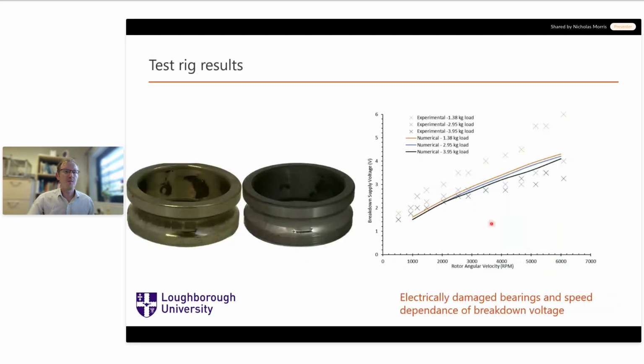So these are some results that we could show just to give an indication of what we can see through the test rig. On the left-hand side of the image here, we have a bearing damaged by applying the electrical voltage across the shaft. And this occurs in less than a day. I think this took 7 hours or something, continuous running at fixed speed. Then on the right-hand side is the same bearing type run under the same conditions, but without the voltage applied across the shaft. So we can run tests to investigate when electrical breakdown of the fluid films within the bearings would take place.